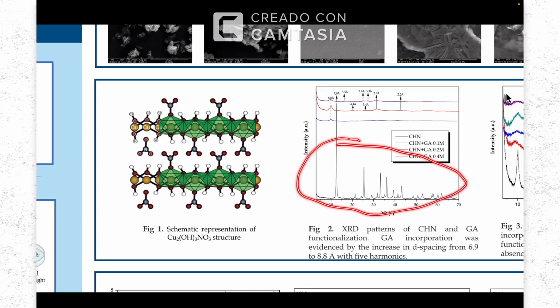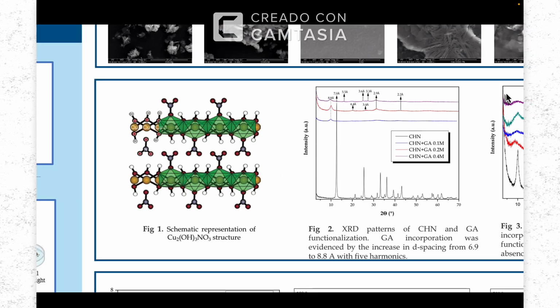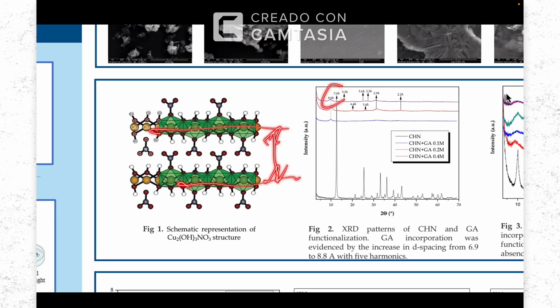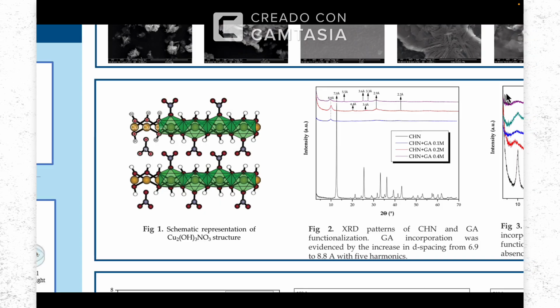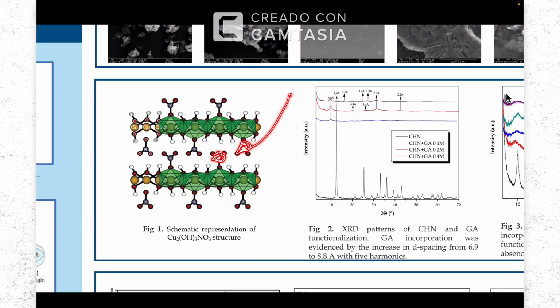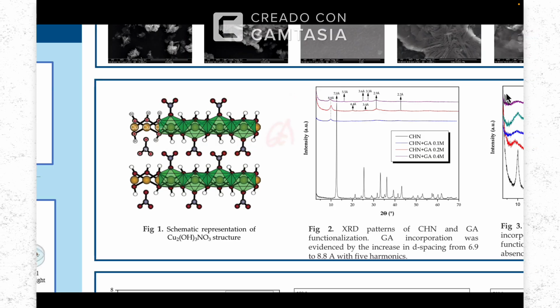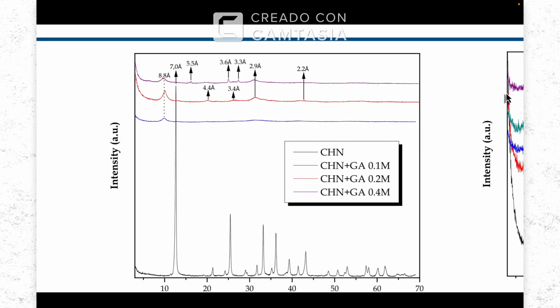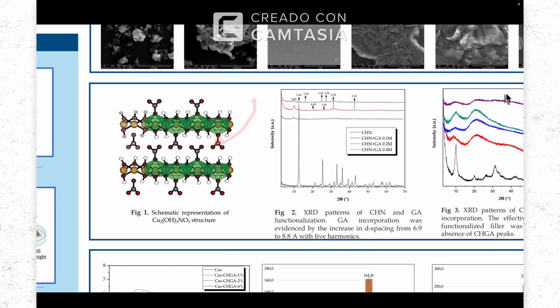The characterization by X-ray diffraction shows the typical pattern for the copper hydroxynitrate material, which is a layer material. This distance is about 7 angstroms, which shows that we successfully obtained the material. But also, when we make the functionalization, we change these nitrate ions by the gallic acid. We can see here in the XRD pattern that the layer has an expansion, which suggests that the gallic acid goes inside between the layers as an intercalated material.